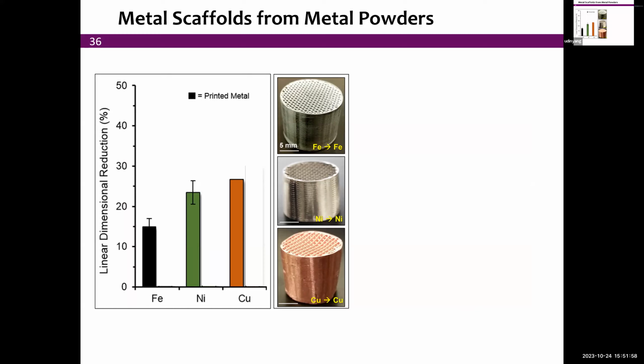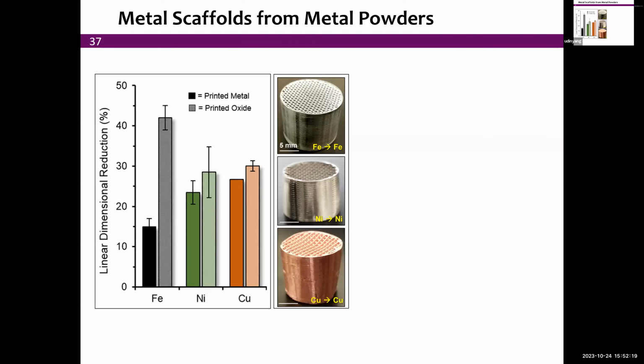not contaminating the metal. The other advantage of using an oxide is that when we burn out the binder, there's no contamination opportunity. Whereas if you burn out the binder in the presence of metallic iron, you may actually collect some of the carbon and end up with an iron-carbon alloy, aka steel, rather than pure iron. Copper, of course, doesn't have this issue because there's no solubility. Meanwhile, you see that the shrinkage for pure iron powders is only 15%, as compared to what we had for the printed oxide, which was 40%. It's a combination of not having to lose the oxygen and also of a better packing of the particles as printed. So there are also variations between the metallic route versus the oxide, a bit more complex route that I discussed.